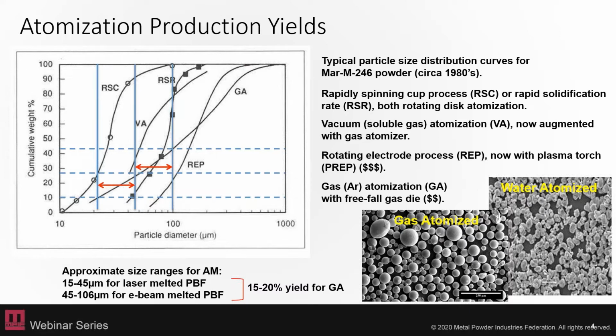So this shows a rapid spinning cup process and then a rapid solidification rate process, which are both based on that rotating disk atomization, where the melt is flown off the edge of a disc that's rotating, and those fine filaments break up into droplets. There's vacuum soluble gas atomization, which is now augmented with a gas atomizer. There's the PREP process, which uses a plasma torch on an electrode that's rotating to break up the material, and then the gas is used to atomize those into fine droplets. And then there's also gas atomization listed on here with a free fall gas die.